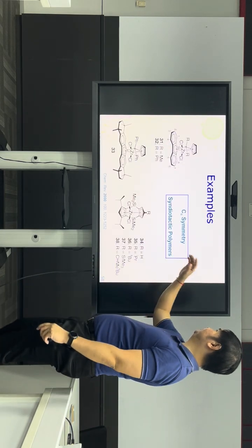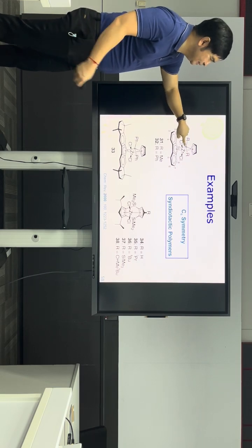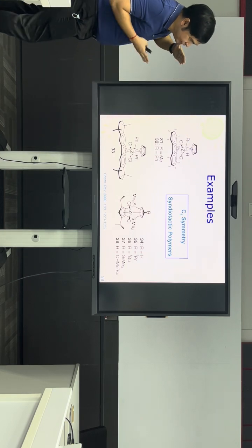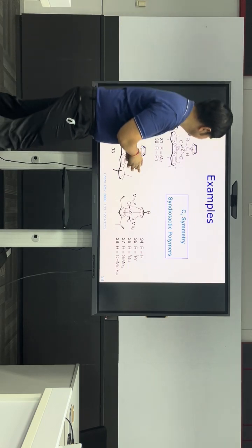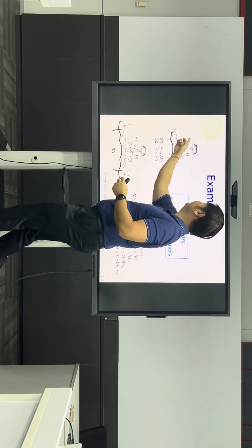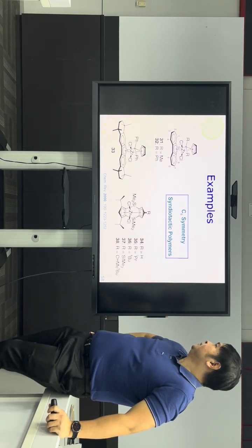Same way for this one. CS is for syndiotactic. In this example, they linked the Cp rings together with CR2. R can be anything, Me2, a proton, many other things. But the point is, if you approach on this side, left hand side is available. So left hand side is good. Approach on this side, now the right hand side is good. It will be left, right, in other words, it's syndiotactic. Up, down, up, down, and so on. Same way for that.